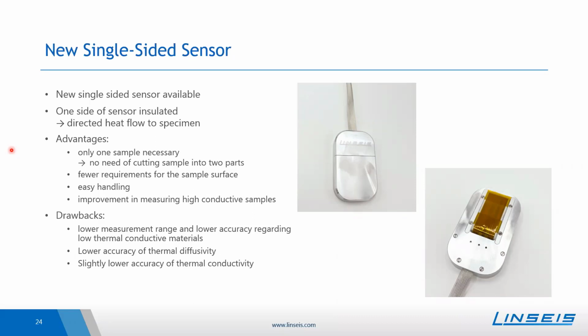And because of that, also just half of the sample surface is necessary. And additionally, it is also often not so easy to prepare the surfaces so that they fit very smoothly on top of each other, to avoid air gaps in between. With this single-sided sensor, this is avoided. It is also very easy to use, on the same level as the other sensors. And because of the insulation on the one side of the sensor, the measurement of highly conductive samples, so especially metals, is slightly improved.